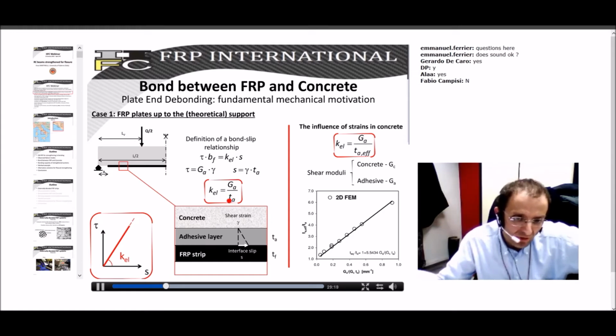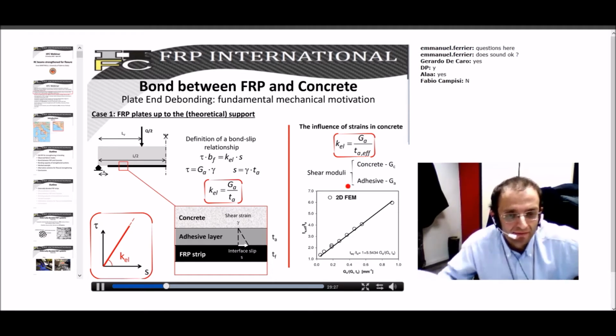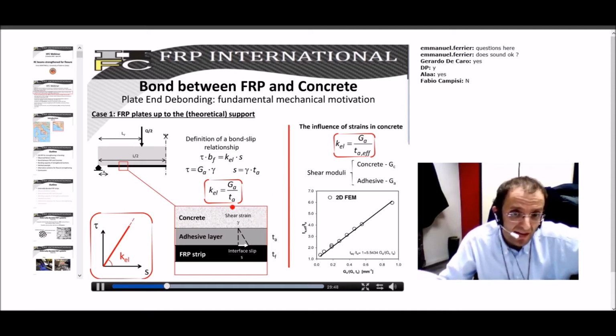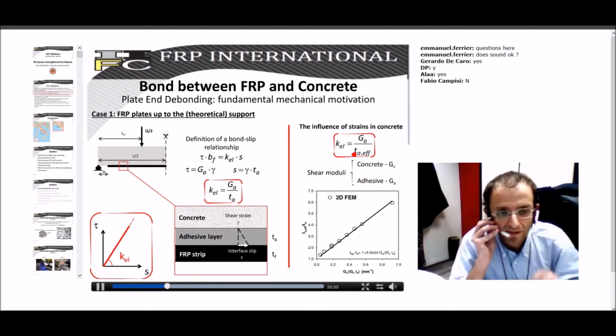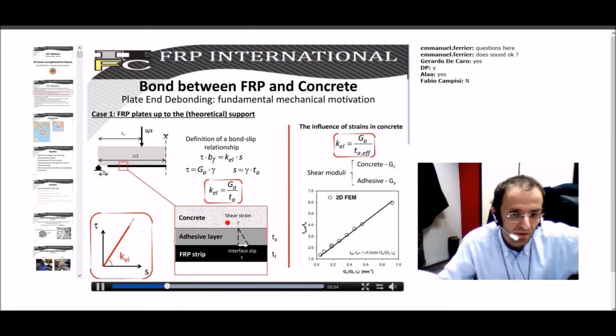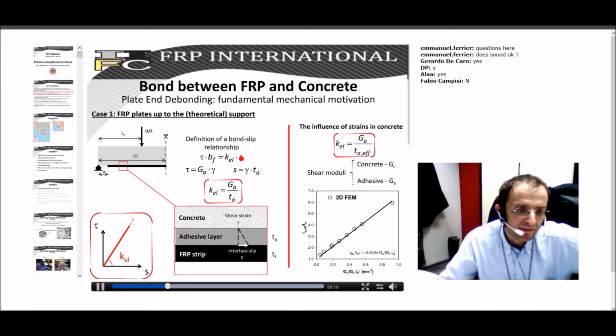this nominal thickness of the layer should be replaced by an equivalent thickness of this layer, which depends actually on the ratio between the shear stiffness of the adhesive and the shear stiffness of concrete. If we have an adhesive layer which is very flexible, T effective would reduce to TA, but T effective is higher the stiffer the adhesive layer is. Usually, if you look at the literature, you'll find suggestions for evaluating TA effective by considering 20 or 30 millimeters of concrete. So T effective is the nominal value of the adhesive plus a certain thickness of the concrete. But this is just a detail in our presentation.